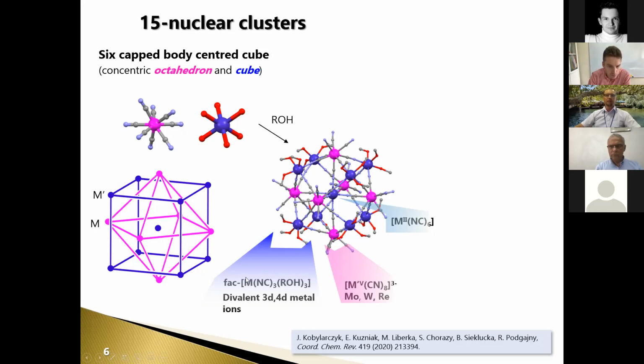And when we take a look at the coordination details, here we have the 3-cyano, 3 alcoholic units, 8 of them. Here we have 6 octacyanometalates, and in the middle, the most interesting one, bivalent metal ions, which are surrounded in almost perfect octahedral geometry by 6 isocyanides, of course, coming from the cyanido-bridges, of the possibility I described at the beginning.